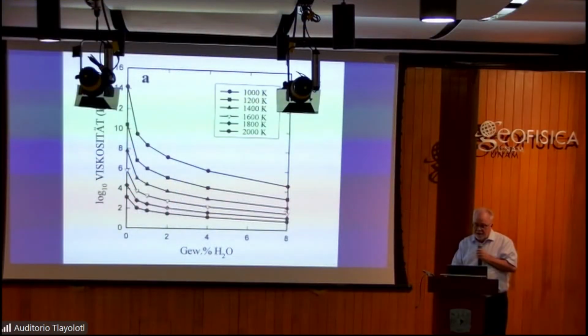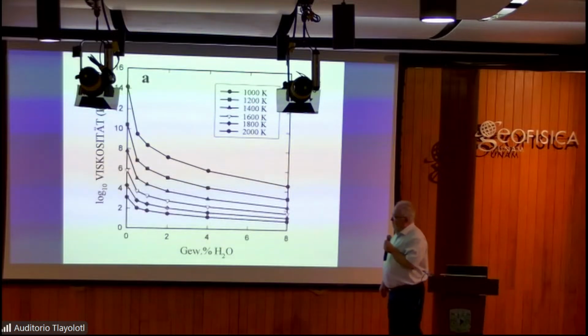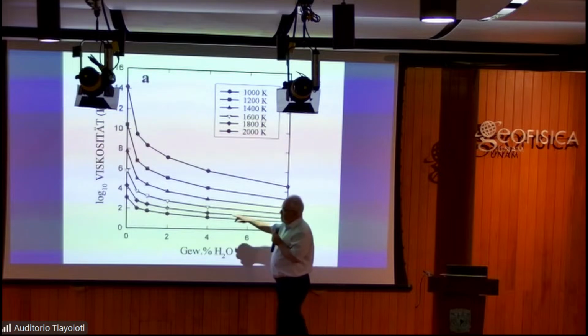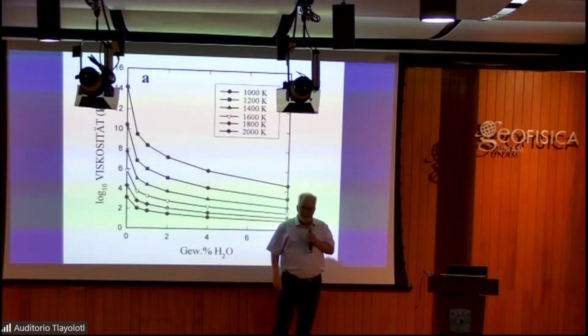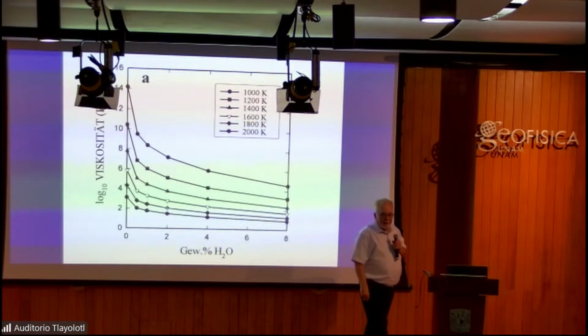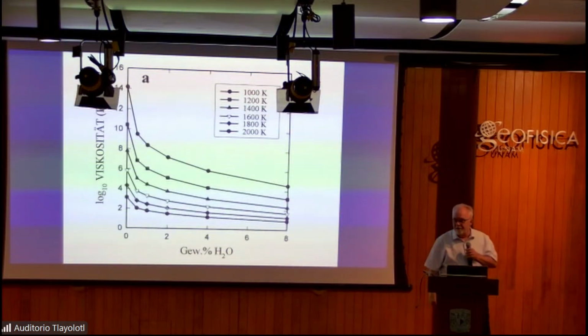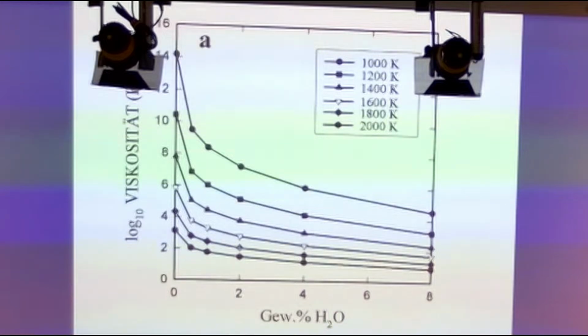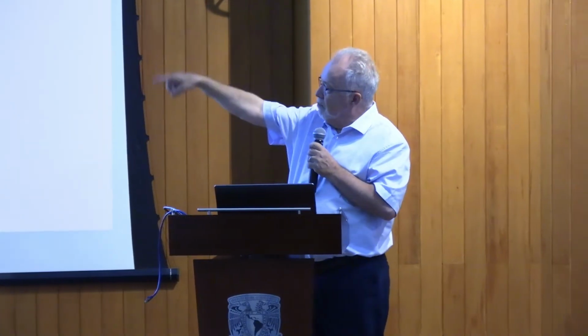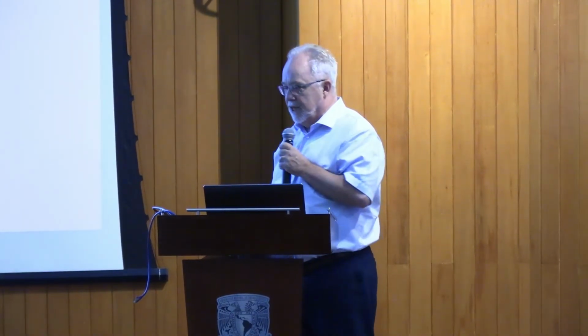but just to let you know, that's a very active area of research, also in Munich, also with our research group. Yeah, and then you have the overriding property which is behind so much of what goes on in these systems, the viscosity. And the viscosity varies logarithmically as a function of temperature, water content, and chemistry. And this was something that inspired me at the very beginning of my career, still inspires me. We're still mapping this out. We have models which are intermediate models in terms of precision, but we're still measuring, trying to get the perfect model for how this one property, viscosity, varies as a function of chemistry.